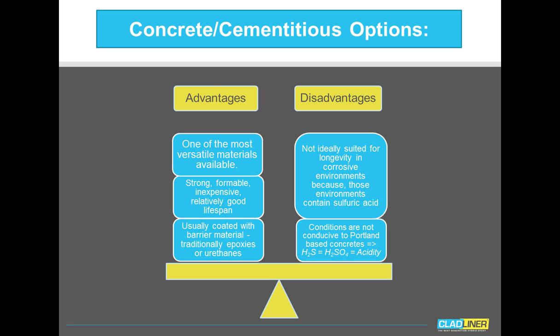But because of the adverse conditions found in manholes, they're usually top-coated with a barrier material like an epoxy or a urethane. The disadvantages are they're not always ideally suited for longevity in this corrosive kind of environment that we're talking about here. They do not handle the acidity well that comes from the sulfuric acid that we typically find in these conditions.